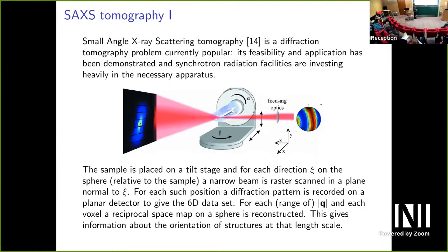Anyway, SAXS, small angle X-ray scattering, really involves the fact that the deflection of the X-ray beam is small, which means that the length scales you're looking at are quite large, right? Because it's reciprocal space. So you're looking for things that are larger than the scale of crystals. And also, at one of these synchrotron light sources, you have a very, very long beam line, to collimate it parallel, and you can put the screen a long way away from the sample as well.